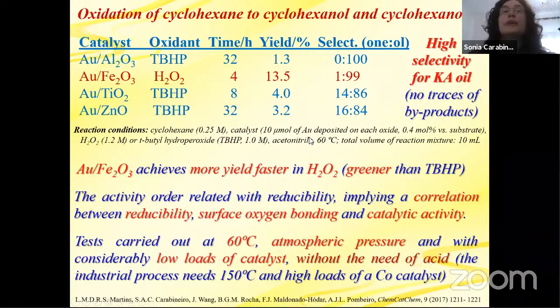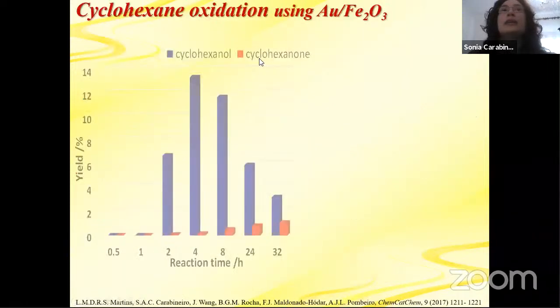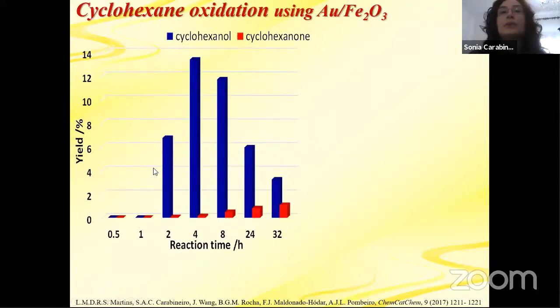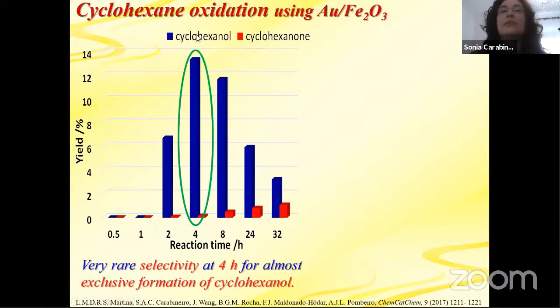And also here, if we look at the cyclohexanol with reaction time, for several reaction times, we see here, like I was saying, this very high and very rare selectivity at 4 hours for almost exclusive formation of cyclohexanol, which is very rare because usually it's a mixture of both cyclohexanol and cyclohexanone that is obtained. And if we do several cycles to recycle the catalyst,